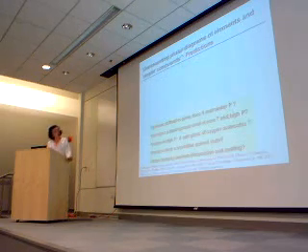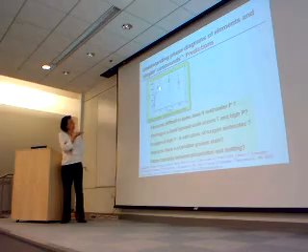And when you do this simulation, you have to check the usual things: that the size effects are under control, that the simulation is long enough, and so on and so forth. So if you do this, for example, this is the melting temperature as a function of pressure of hydrogen. And these are the simulation points that we have done. See, these triangles here are all simulations that we have done to finally bracket the melting temperature.